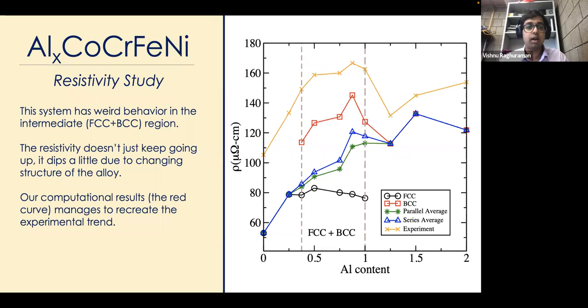You could also calculate electrical resistivity, which is again a very important property. So here is an electrical resistivity of aluminum, cobalt, chromium, iron, nickel. And here you can see that this system has sort of interesting behavior in this middle intermediate region. And our computational calculations can recreate experimental trends. So which means we can get accurate electrical resistivities using computational tools.